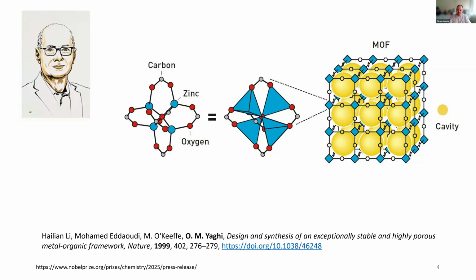And it was really the demonstration of this MOF-type framework in this paper from 1999, where Omar Yaghi and co-workers were able to demonstrate that these frameworks are able to withstand solvent removal, and in addition to that, featured extremely high surface areas, almost an order of magnitude higher than comparable zeolite materials, which were sort of the benchmark for microporous materials at the time.